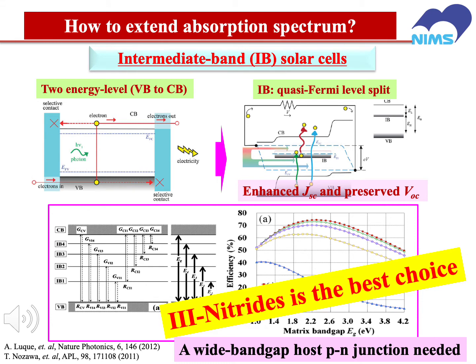And here we propose the concept of the intermediate band transition in the solar cells. So typically the solar cell has the p-n junction structure, with two energy levels, absorption only from the valence band to the conduction band. However, if we introduce another band which is inside the band gap, the absorption can be realized from both the valence band to the intermediate band and the intermediate band to the conduction band, and combined with the band gap absorption, we can observe the band gap absorption and sub-band gap absorption, and then extend the absorption spectrum.